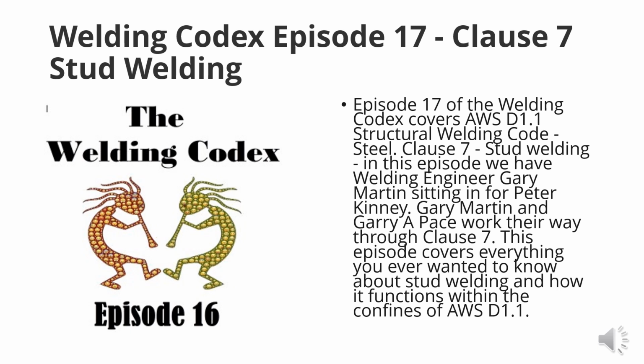And what's interesting is the bridge code borrows or steals a lot of content from D1.1 and then massages it to meet the bridge requirements. They have their own stud clause, but they call out a different material. This is ASTM A29, which is hot rolled bars. They actually call out a cold drawn spec material. The tensile strength is similar though.